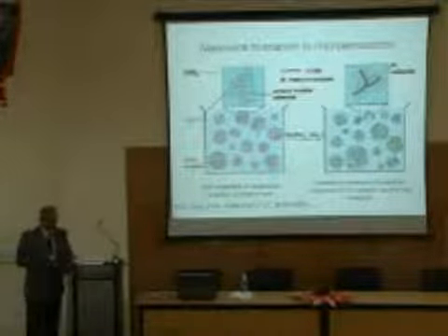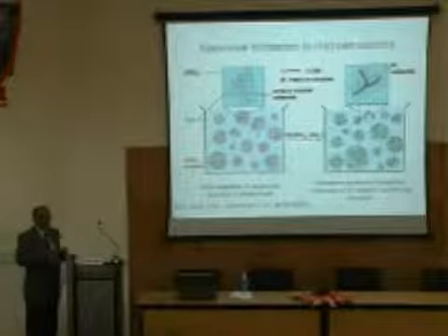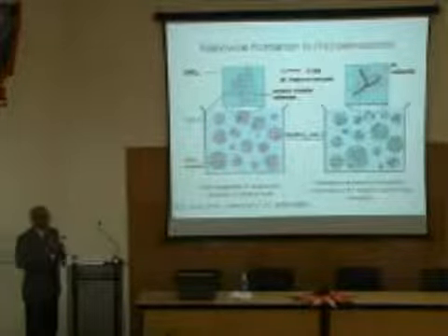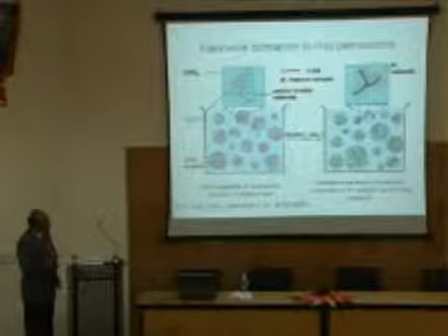To make one particular solution of a microemulsion, you need 3-4 components. Okay? You may need alcohol, you may need alkane and some water, and the thermodynamics will make the molecules align in a particular fashion because it has to reduce its energy, right? So depending on the nature of the initial molecules that you take, you will get different types of structures. In this case, it's like a worm-like micelle.